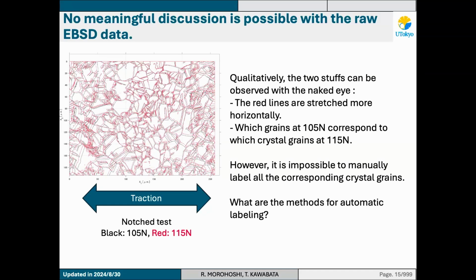However, with these raw forms, we couldn't do any quantitative analysis. For example, this is the overlay of the grain boundaries of the notch test. The black line is showing the EBSD at 105 newtons, and the red one is at 115 newtons. From the naked eye, 2 things can be observed easily. One thing is that the red lines are stretched mostly horizontally, and then we could identify which grains correspond to the grains on the other load. However, obviously it's impossible to manually label all the correspondences. So we need a kind of automation to detect the deformation of the grains.